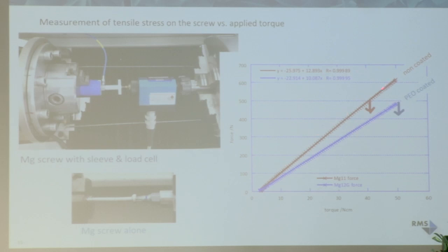The non-coated screw, you see, you reach at a torque of 40 Newton centimeters, you reach 500 Newton of load. And the PEO coated, we reach it only at 50. This is because the coating is rougher and it has more friction with this plate.